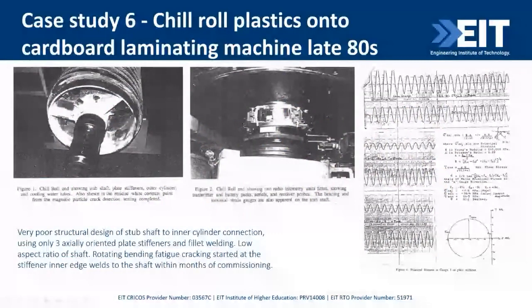And for some reason, this was designed with 3 gussets, only 3 gussets between the chill roll and the stub roll. Plate, circular plate in here to end it off. But as soon as you see that, you know this is a problem. The high bending moment right there at that cross section is going to tear this weld joint here on the inner edge of these gussets, and it did within a matter of weeks. So this thing was designed with no thought to fatigue, I'm sorry to say, not only in that overall concept of the 3 gussets, but also in the poor fillet welding, etc.